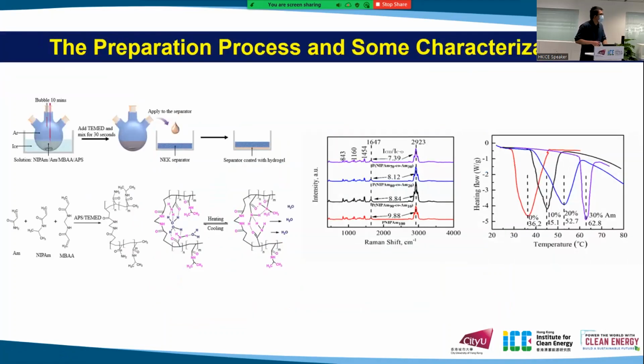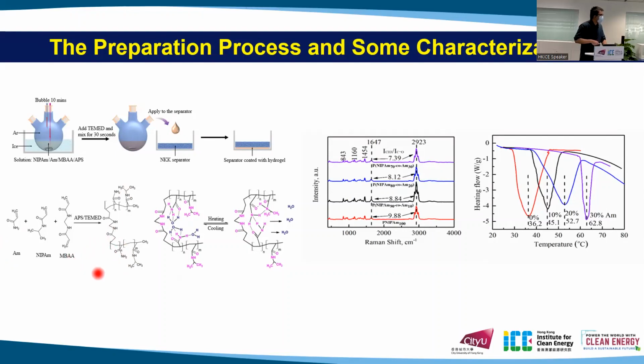We choose AAm and NIPAM, polymerized with the cross-linker MBAA. And we try to control the amount of AAm, so we can control the lower critical solution temperature. Because we want to use it at room temperature, and we do not want it to stop working at a temperature which is not high. And here we also carefully choose the substrate to control the thickness.